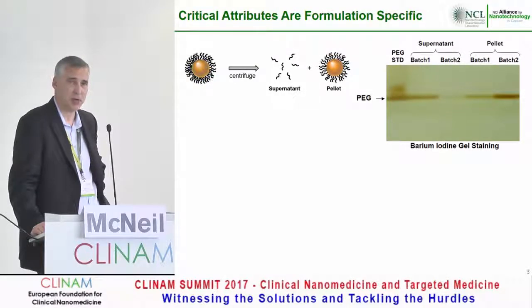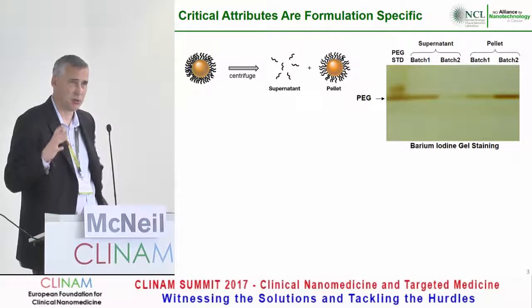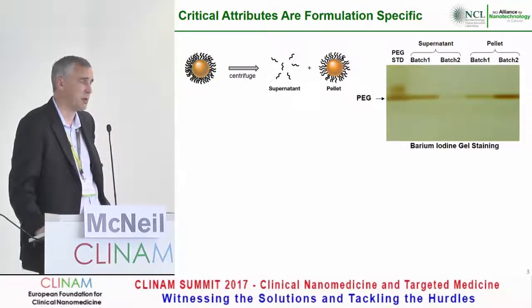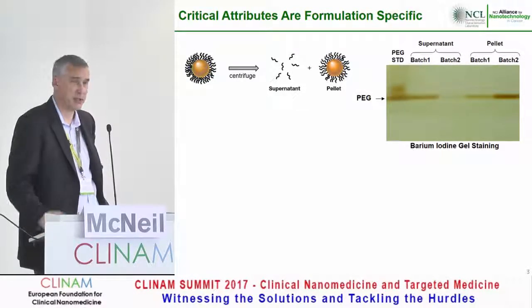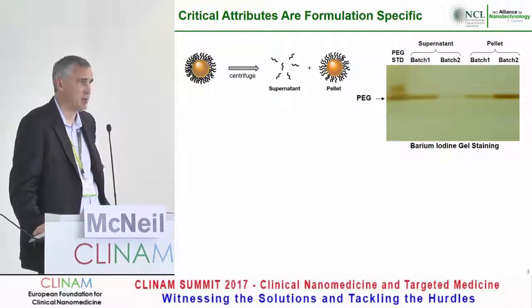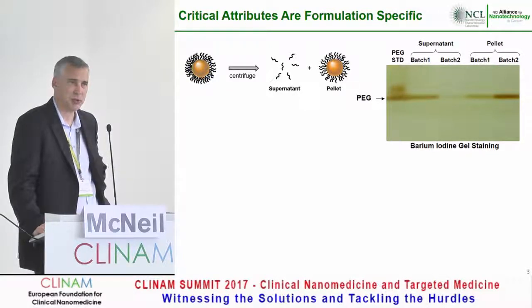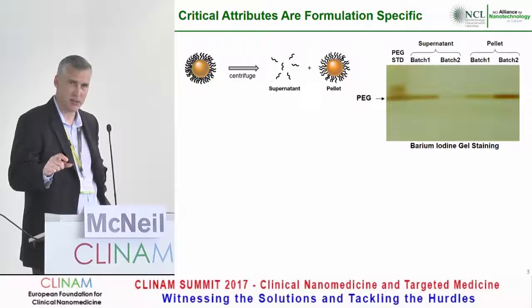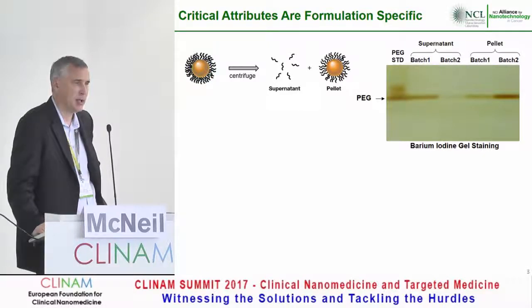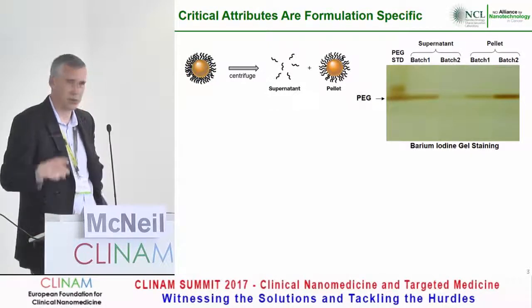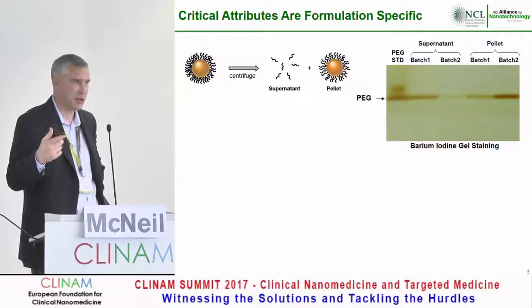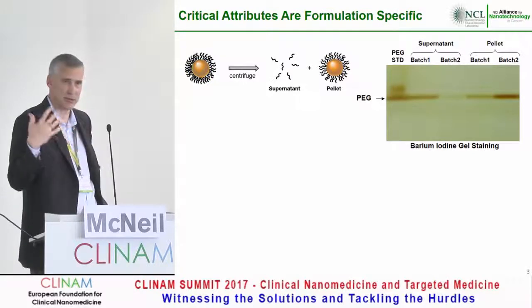But we found that through our traditional methods, we did DLS and other things, we were not able to pick up a difference. But you truly have to know the measurand that those instruments are recording. In the case of DLS, it looked at the hydrodynamic radius, where the two species looked identical.